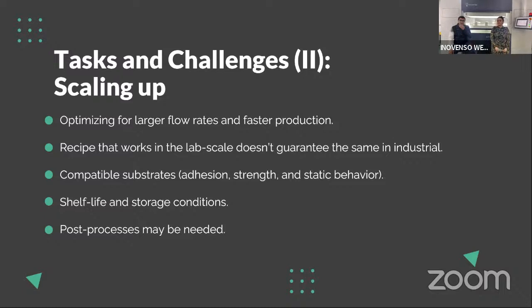Substrates are also pretty important. You need to worry about its adhesion. So you might be able to set up a pre-coating, or maybe coat it in adhesives before, but if it has low adhesion, that could be very, very problematic for you later on, especially if the nanofiber layer can just peel off. So the substrate needs to have relatively good adhesion for your nanofiber layer. So adhesion is one thing.